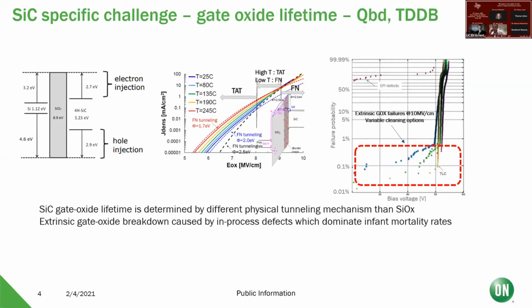The first thing that happens, or maybe the other thing in every semiconductor reliability, is the interface with dielectrics. Silicon oxide is rather blessed with having a near perfect semiconductor insulator interface. That's in addition understood now for 5-6 decades with lots of study. You see on the left in this band diagram how different the band gap picture looks from a silicon carbide point of view, which is 3 times the size of silicon and has different band alignment. So as seen in the middle, the tunneling effects are different. They need to be characterized or recharacterized.